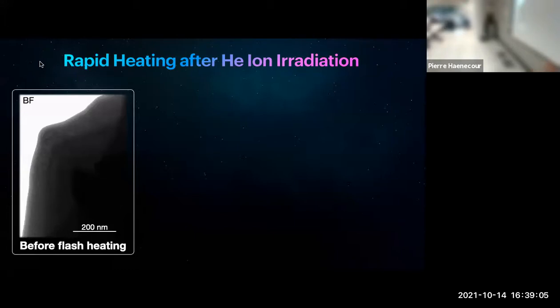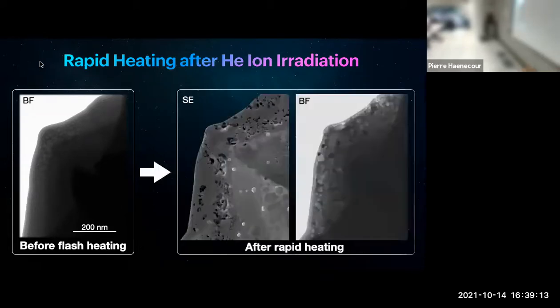If we look at what happened to the actual edge where there are those trapped bubbles, it's relatively dark, but it's basically showing you trapped helium on the edge of the sample. And then after the heating, you basically release all those bubbles, so you can actually physically see the holes in the surface of the sample. It's a secondary electron image, showing you the surface of the sample, showing that you release all the helium and then form nanoparticles all around.